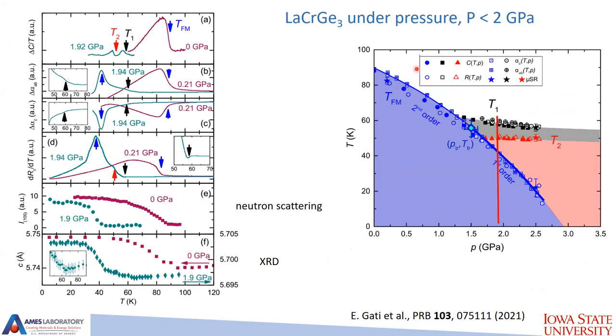Fine. You can look altogether at thermodynamic measurements plus resistance measurements along the C axis plus neutron scattering plus X-ray scattering, both at zero pressure, very close to it, or at 1.9 GPa. And you see the consistency. So for zero pressure, all of these measurements have a feature corresponding to this ferromagnetic transition and nothing more.